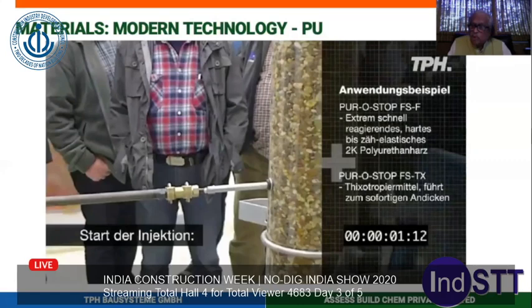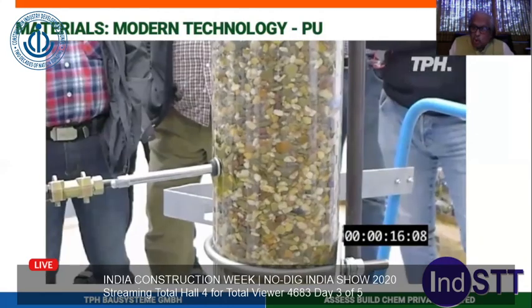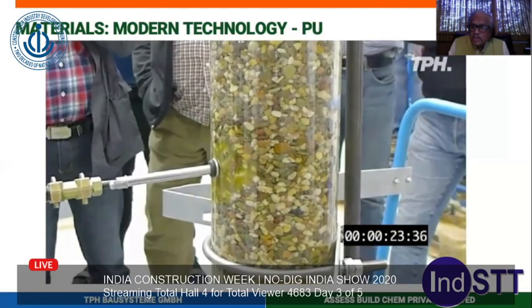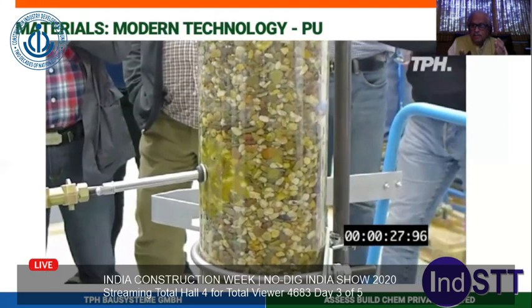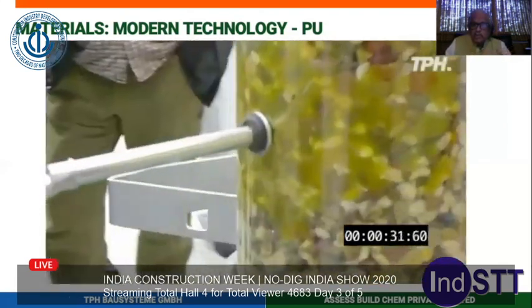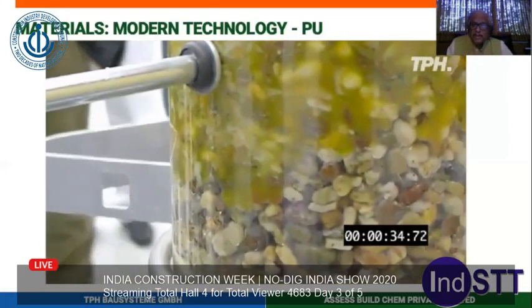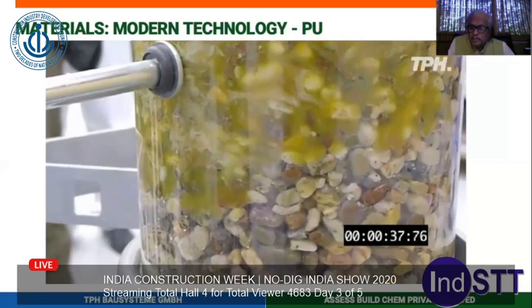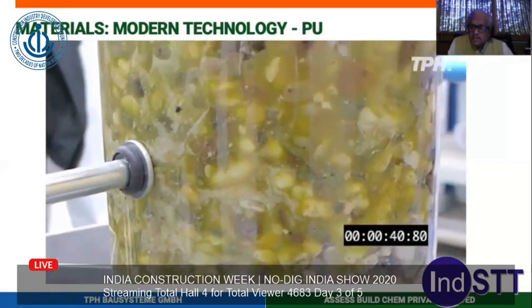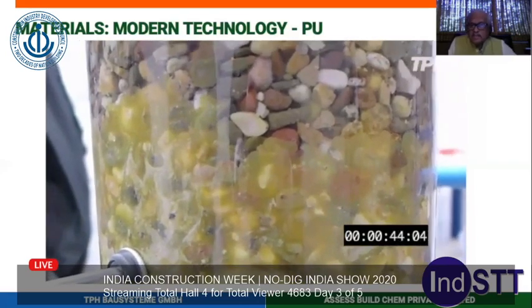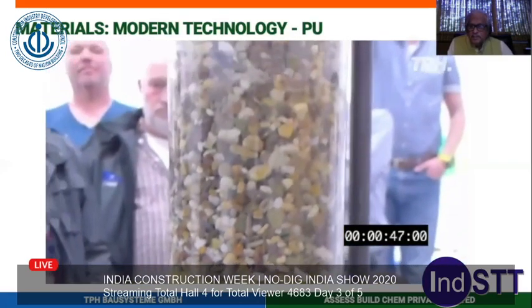So you start injecting a structural polyurethane. It's only 7 seconds. First thing, the speed of reaction is very, very important. In 7 seconds, in fractured rock, you're putting the materials. About 17 to 20 seconds, or 20 or 30 seconds, is required so that the material can spread all around, because you cannot just make it set within 1 second or 2 seconds, since the material has to also spread all around. Then it has a foaming capacity. When it comes into contact with water, its reaction starts within about 30 to 40 seconds. The reaction has slowly started, and it is a structural permanent solution.